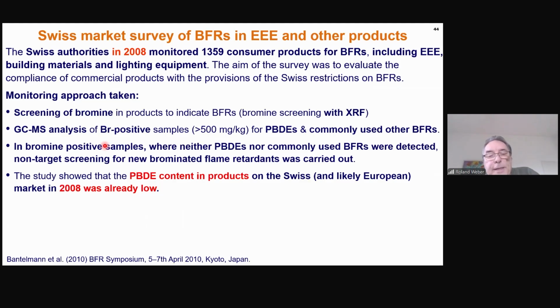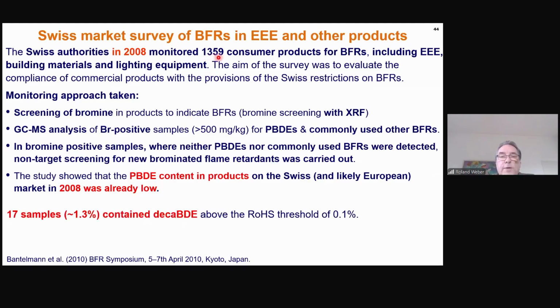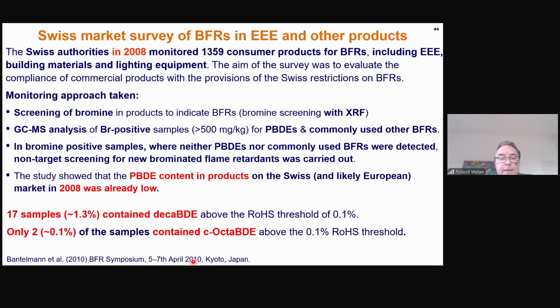So the study showed that the PBDE content in products in Switzerland and likely the European market in 2008 was already low. From the 1,360 consumer products, only 17 samples, this is 1.3%, contain deca-BDE above 1,000 milligram per kilogram. And only 2 samples, around 0.1% of the samples, contain c-OctaBDE. So you see only very, very few samples in 2008. And before you saw with the televisions from the 1980s, 1990s in Nigeria, that a large share of the products were flame retarded with PBDE.